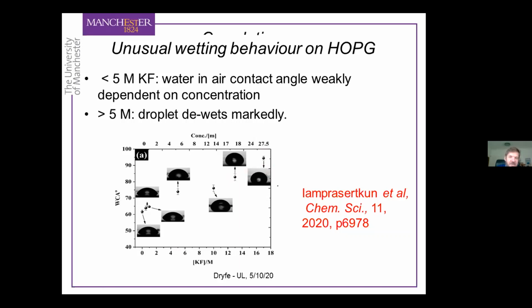And physically, it's easy to understand why this is. There isn't enough water to solvate the ions properly, so the water doesn't spread over the surface. And again, maybe it exists, but I've not been able to find any literature on contact angles of these very concentrated electrolyte solutions. And we reported all this highly concentrated behavior in a recent paper in Chemical Science, if you're interested in reading about this in more detail.